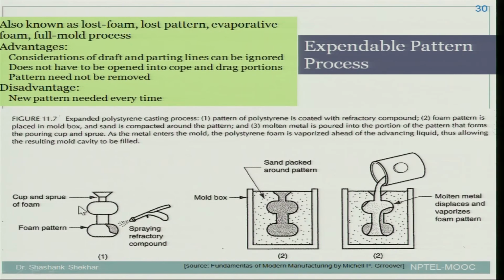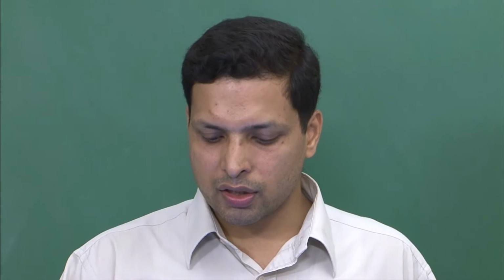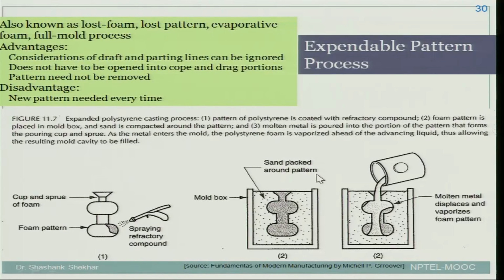Inside it you make a polystyrene or foam pattern, and you spray it with some refractory material so that the surface finish comes out good, and then put the sand around it so that the sand again takes the shape around it. Now instead of taking this polystyrene foam out of the mold, as we did in sand mold casting using a wooden pattern, here we can directly pour the liquid metal into it.